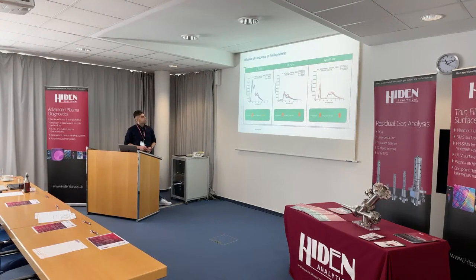This is the influence of frequency on different pulsing modes. So in the case of LF pulse, as the frequency increases from 0.1 kHz to 10 kHz, the integral intensity almost remains constant. In the case of HF pulsing, increasing frequency leads to lower integral intensity. And in the case of sync pulsing, increasing frequency leads to higher integral intensity. So the IEDFs are here.